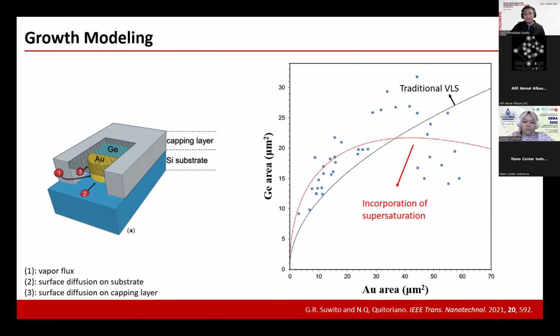However, of course, I agree with you. We found that our data has a lot of variance and a normalization is required. This variation is basically due to the mechanical deformation of the capping layer. So if you remember, because we mechanically inhibit the vertical growth, we have some films go this way, but maybe some films go this way, some films go too big and then agglomerate quite big. So there is variation on the vertical axis.